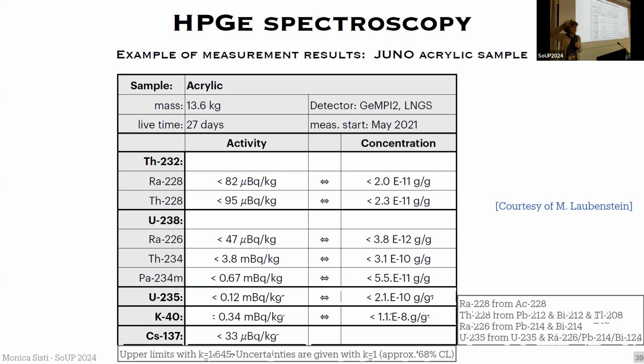The liquid scintillator is inside the acrylic vessel, so we have stringent requirements for the acrylic vessel that contains it. But the glass of the PMTs is usually quite dirty, and the glass of the PMTs that are reading the light is also of great concern. That's why, if you remember the picture, there is at least 1.5 meters of water between the PMTs and the acrylic vessel. This is to shield the background of the PMTs, which are probably one of the most serious sources there.